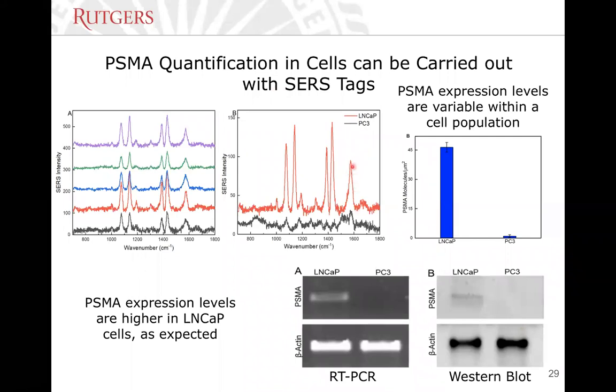And as you can see here, the signal that we observe is the SERS spectrum of the Raman reporter with which we had functionalized the nanostars. And so we looked at the presence and the intensity of these peaks to really assess the presence of the PSMA and quantify it. First of all, we realized that by looking at different cell populations of the same cell type, so for instance, this is the LNCaP population, different cell groups, and we average the signal from the different groups, we see that every group has different expressions of PSMA, which is in line with the heterogeneity of the disease.